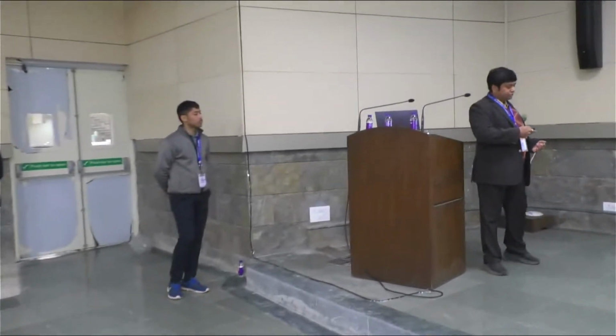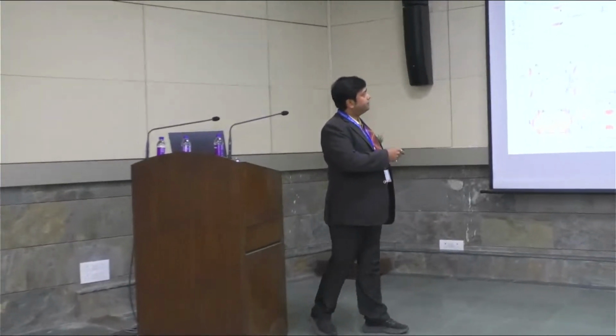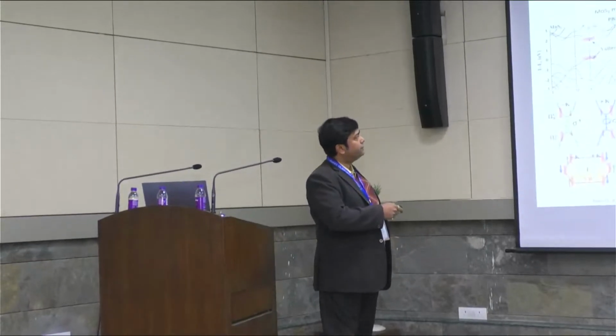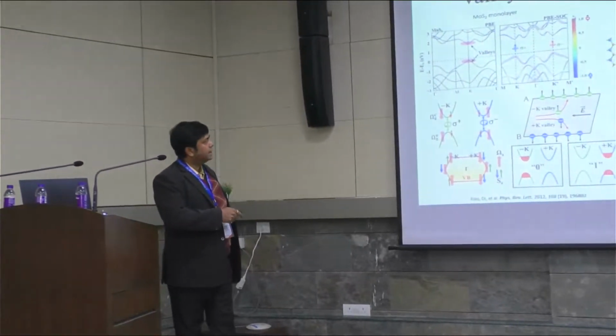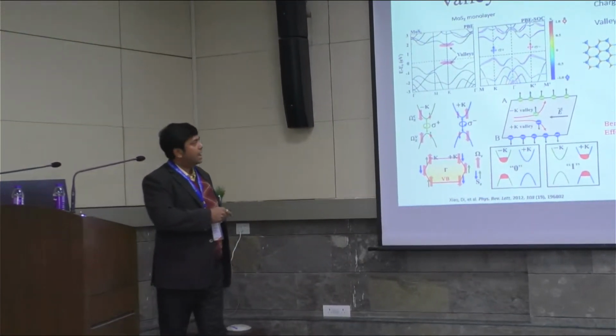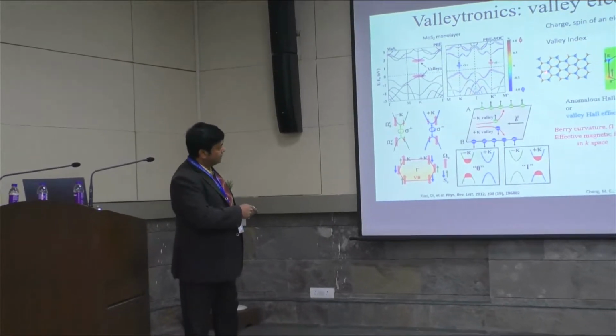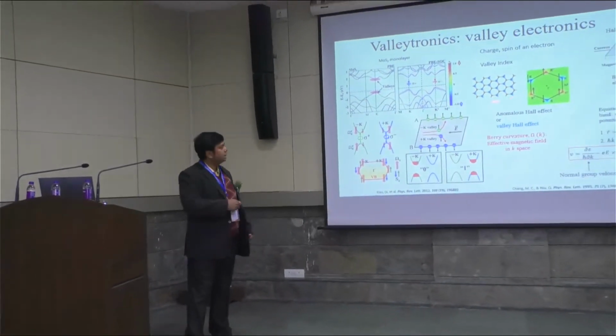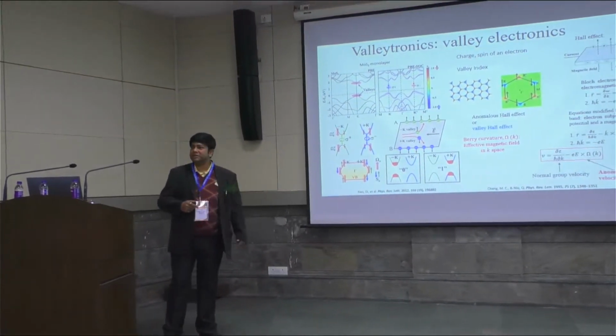And likewise, the single layer MoS2 shows these valleytronic properties, the Valley Hall effect. I'll be talking about that in the next few slides. The bilayer doesn't show it. As you can see here, for the bilayer the Valley Hall voltage curve is flat. It doesn't vary with the voltage. Now, apart from the charge and the spin degrees of freedom of an electron, another degree of freedom arises in a single layer MoS2. As you can see, the inversion symmetry is broken here. This is the top view of MoS2. The two atoms are different here. The inversion symmetry is broken.